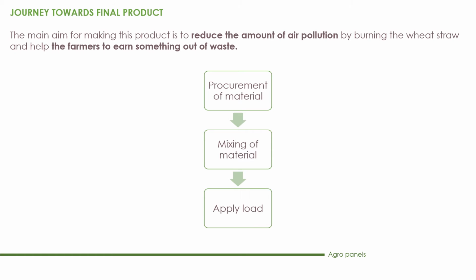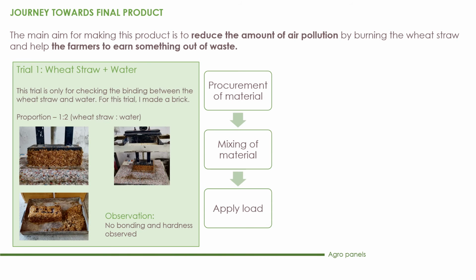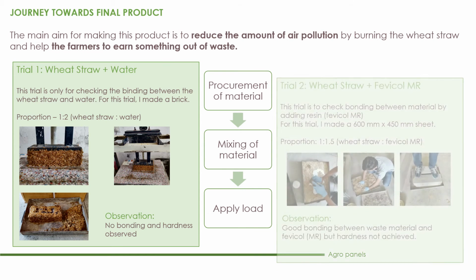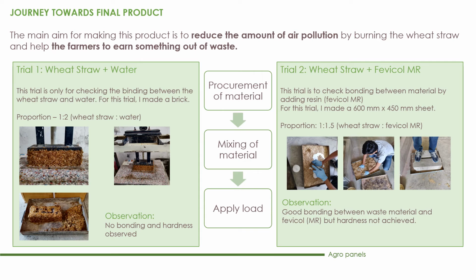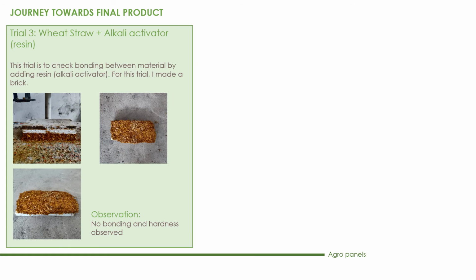This mixture is placed in a mold and compressive load is applied for better bonding. Trial 1 included making a brick out of wheat straw and water to check its binding, but resulted in negligible binding and hardness. To resolve this, wheat straw was mixed with Fevicol in the form of a 600 by 450 mm sheet. By observation, good bonding was observed but it wasn't stiff enough.